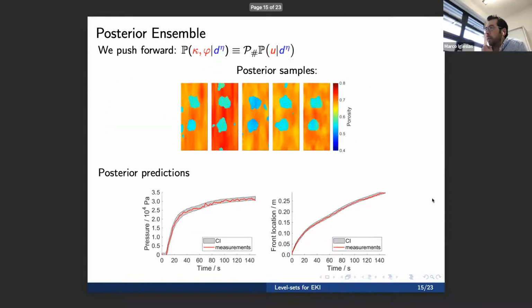But we do the posterior, so we run Kalman on the hyperparameters and all the deep parameterization. We push forward into physical space to compute the posterior samples, and we start seeing that we get the shape of the defects that we had before. There is still a lot of variability in the samples, because we didn't consider a very small noise, to make it realistic. For the posterior predictions, when I pick each of these samples and run the simulator forward, we get this nice uncertainty band. So everything works as we would expect.